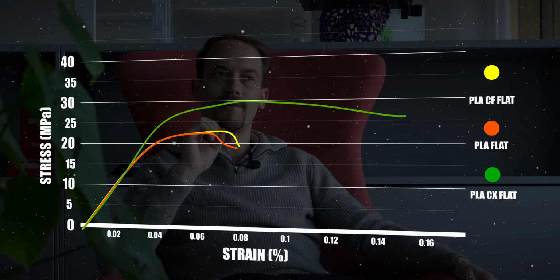I'm just not sure if it's actually that the coextrusion itself and the layer bonding does something positive, or if it's just because of what they also claim, use longer carbon fibers. So the longer the fiber is, the more energy it can take, even though it can move around in the polymer itself. So we might have to look into that a little bit more, but I would say that's a fact. So the second claim was that they have stronger layer bonding, and we tested that using tensile strength testing,